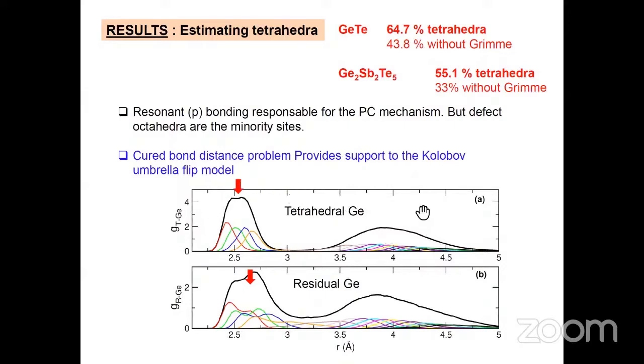So here's the pair correlation for the tetrahedral. We see something very close to what we would expect for selenides or sulfides: a very well separated peak between the first peak and the second peak of neighbors. Here we have indeed 4 neighbor distribution functions which are very well separated from the 5th, 6th, etc. neighbor functions which contribute to the second shell of neighbors.